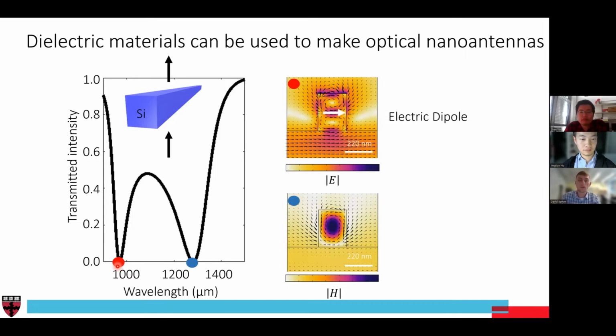So if you think of a canonical, standard electric dipole where you have the electric field circulating around, or in this case, a magnetic dipole here at the bottom, where you have an electric field circulating around in this orientation, we're able to shape the local structure that this light takes on. And so this is interesting. We can design a lot of things with these optical resonances. One challenge here is that the transmitted intensity goes to zero, so you don't have a whole lot of light going through, which is maybe not that useful.